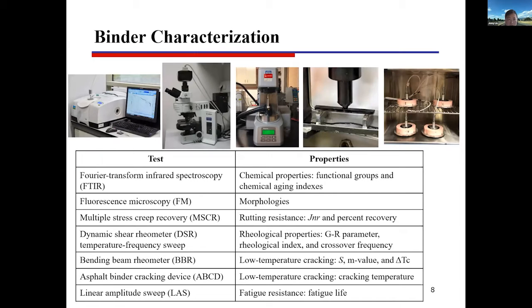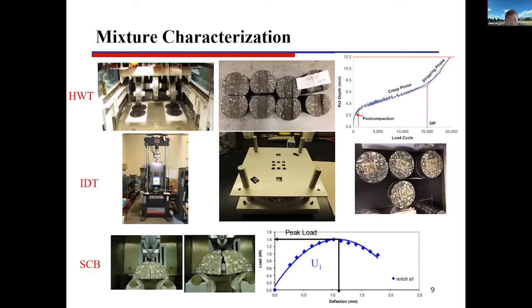This slide summarizes the tests we conducted for binder characterization, including FTIR and fluorescence microscopy for chemical and morphology study, and also other tests to evaluate the rheological properties, low temperature cracking and rutting resistance, and also fatigue resistance. And this slide summarizes the performance tests for mixtures, including the Hamburg wheel tracking test, indirect tension testing to evaluate low temperature performance, and also the semicircular bending test to evaluate the cracking resistance.